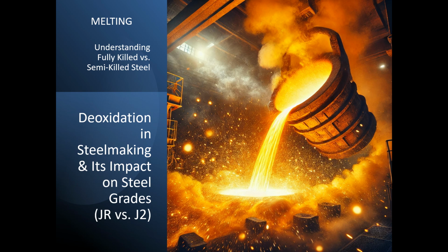And so the steel is covered with something called cover fluxes, and that prevents the oxygen from diffusing into the molten steel. And the cover fluxes also help control the alloy chemistry. So things like manganese have to be added to the steel. And because all these elements melt and vaporize at different temperatures, cover fluxes are put on top of the steel to control how it responds to the environment.